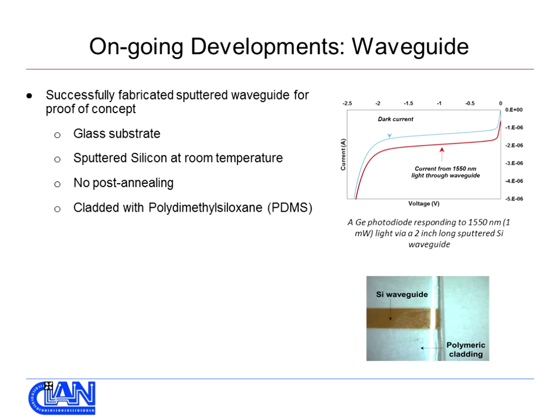So what have we developed so far in the waveguide technology? What have I participated in at Tuskegee? So far, we've successfully fabricated a sputtered waveguide for the proof of concept. So silicon was sputtered onto a glass substrate, and we sputtered it at room temperature, and we did not post-anneal. So this was one of the cases, the simplest case, where we didn't do any heating to the silicon, which is ultimately our plan, but this will serve more as the control group for our experimenting.